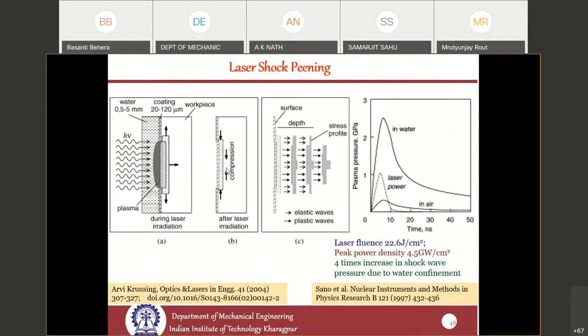Another important application is laser shock peening, similar to conventional shot peening, used to introduce compressive stress to improve the fatigue life of a component. Here you have the workpiece, on which you put an absorbing coating of black paint or black tape, in which the laser beam gets absorbed and forms plasma. This also protects the workpiece surface. On top of that, you put a water layer of about 2 to 3 millimeters.